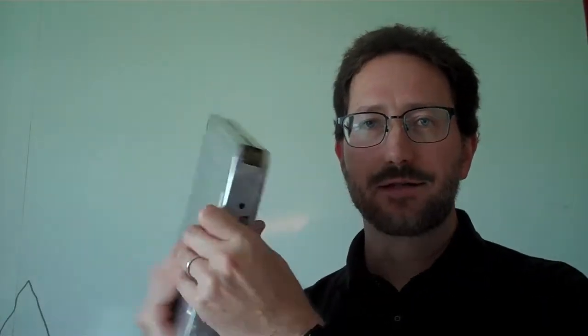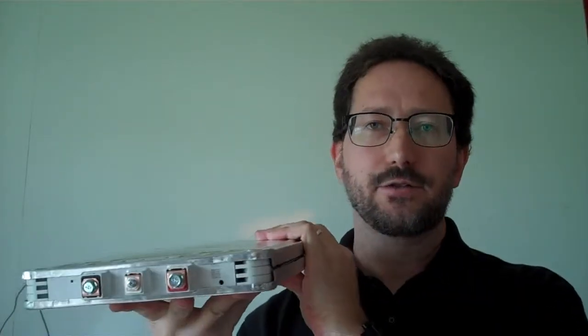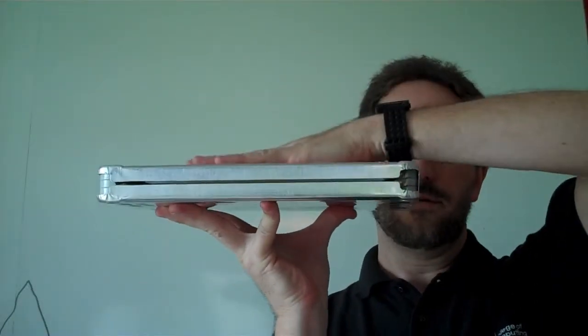It is a prismatic cell, it means it's a rectangular prism, because they're square pouches, and it is not cylindrical, and so because the cylinders will maintain themselves, these guys need external pressure, so they have to be clamped this way when they're used. So you can hold on to them unclamped, but if you're going to be charging or discharging, you need to clamp them. And so they need to be clamped to the same size as they are in the Nissan Leaf, which is exactly 1.333 inches, so 1 1/3 inch.